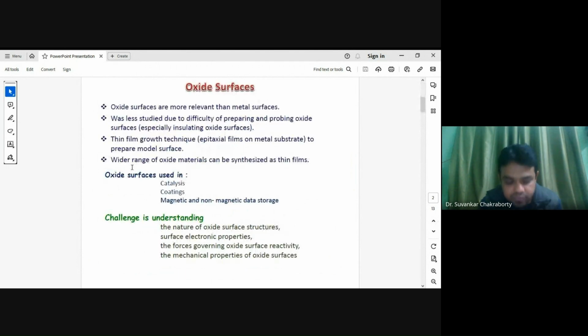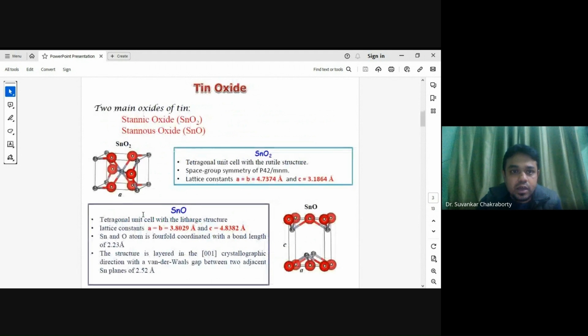So why oxide surfaces? Mainly because if I have a metal surface, most of the time the metal surface is always covered with some oxide because of oxidation. So if I don't know the oxide surface, then I cannot know the behavior of the total material. And oxide surfaces are used in catalysis, coatings, and magnetic and non-magnetic data storage. But the main challenge in oxides is the preparation of epitaxial film so that we can study the band gap or band structure clearly. Now, as a sample, we have started with tin oxide.